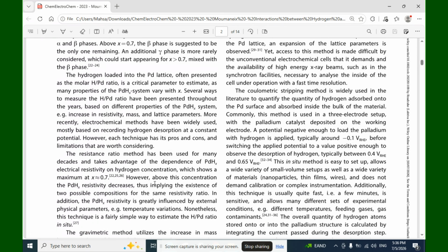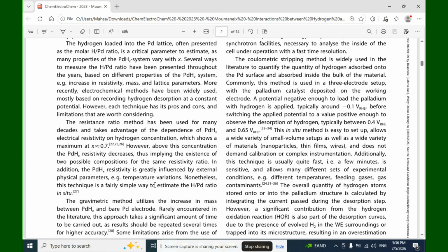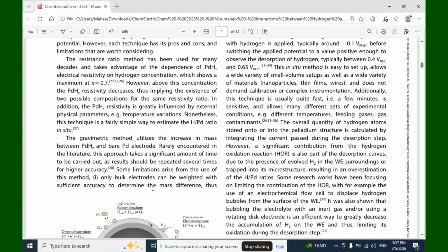The resistance ratio method has been used for many decades and takes advantage of the dependence of PdH_x electrical resistivity on hydrogen concentration, which shows a maximum at X equal to 0.7. However, above this concentration, the PdH_x resistivity decreases, thus implying the existence of two possible compositions for the same resistivity ratio. In addition, the PdH_x resistivity is greatly influenced by external physical parameters, for example, temperature variations. Nonetheless, this technique is a fairly simple way to estimate the hydrogen palladium ratio in situ.